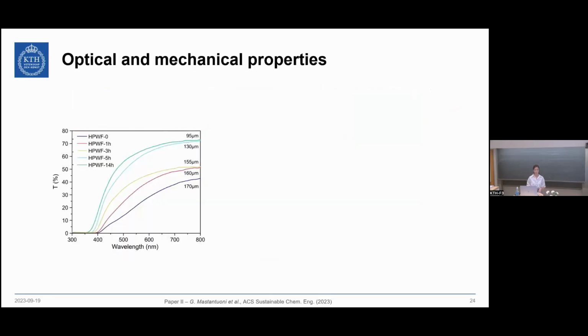Regarding the optical properties of this material, we could see that there is a progressive improvement of the transmittance the more we push sulfonation. So the materials that are both 5 hours and 14 hours show the highest transmittance. And this is a joint combination of fewer gaps as well as thinner films. At the same time, all of these materials present UV blocking, and the reason for this is that the functional group in lignin can actually absorb part of the UV spectrum.